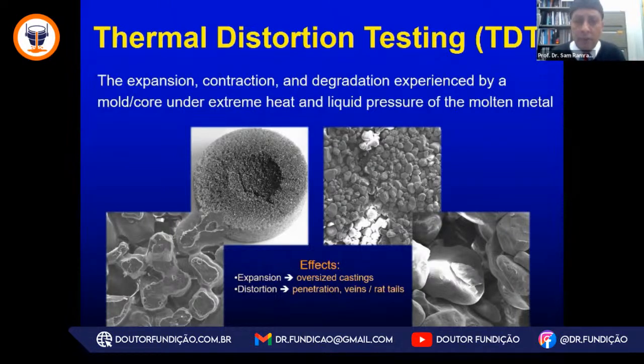Let me stress the importance of liquid. Again, when the casting is solidified, the load against the mold or core for the chemically bonded sand is just down in Z. But as we fill that casting with the liquidous hot metal, the thermomechanical stresses are important. And we understand what these liquid pressures could be all the way through solidification. And if we can express that through rho GH, we can develop testing that better subjects our chemically bonded sands to get real-time smart data. When I say real-time smart data, I mean time series data about our chemically bonded sands.